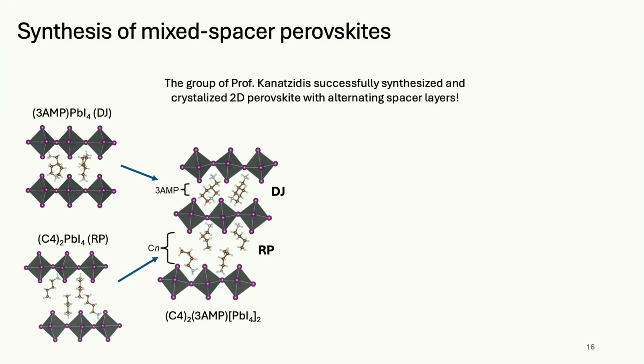Okay, so this is an example. You see, this is just using butyl ammonium. So there's 4 carbons here and an ammonium group, and this is the Ruddlesden-Popper phase. And then this one is this molecule called 3-AMP. It has a nitrogen there and a nitrogen there. So it fills the whole thing and makes a Dion-Jacobson phase. So amazingly, if you provide to the reactive system both of these molecules, you get a halide hybrid perovskite with a perovskite layer and then the 3-AMP, and another perovskite layer and then the butyl ammonium. And then it repeats, perovskite in this guy, perovskite in this guy. So it actually makes a 2-material sandwich.